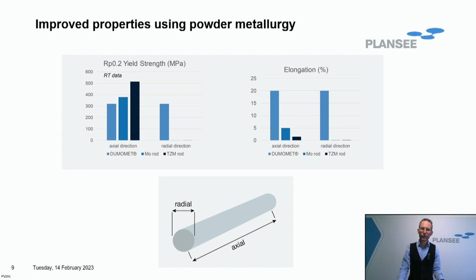If we adapt the production process, we can produce a new molybdenum material called Dumomet. It shows a little bit lower yield strength, but it is independent of the direction. For axial and radial, it shows around a little bit more than 300 megapascal. On the right side, with elongation, you can see that Dumomet is exceptionally ductile, both for the axial and radial direction.